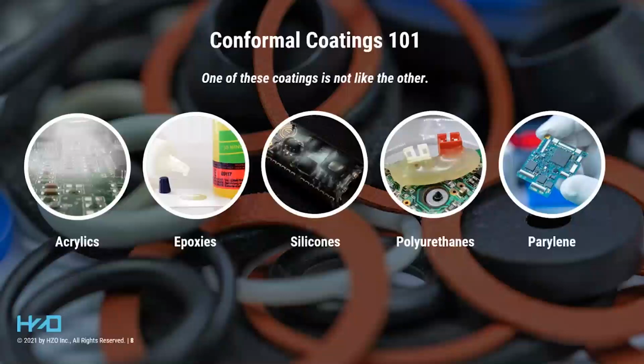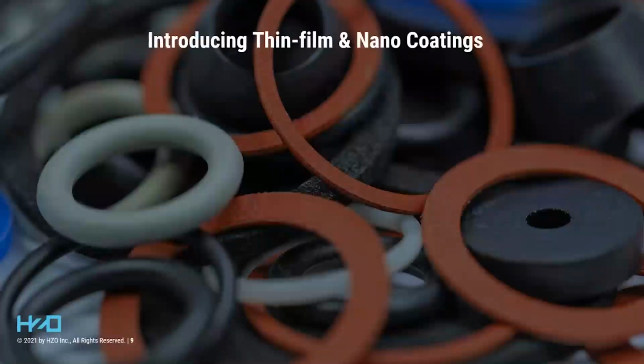As I mentioned, traditional materials tend to go down fairly thick, so for an effective coating, they're typically in the 50 to 250 micron, or 2 to 10 thousandths of an inch. But I often encounter them in the several millimeter range. To contrast, the thin film materials we'll cover shortly, including parylene, are generally referring to coatings under 20 microns, or less than a thou or a mil, and those can be as thin as 500 nanometers. So let's look into some of these technologies.